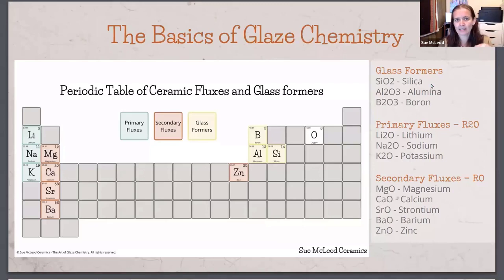And then everything else is added to the silica in order to either help the glaze to melt at the temperature that we're firing it to, or to prevent the glaze from running onto the kiln shelf. We use fluxes to lower the melting temperature of silica. So silica all by itself melts at a very high temperature. It's around cone 32. And so if you think of our cones, our witness cones, a lot of us are firing to cone 6 or cone 10, maybe cone 12 at the most. Silica by itself melts at cone 32.